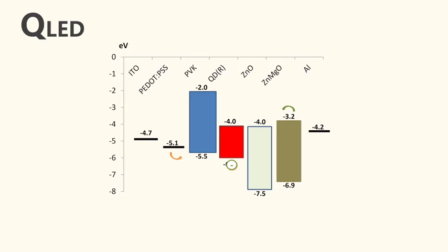This device adopts the EL characteristic of QDs. The full width at half maximum can be as sharp as 20 to 40 nanometers. The research for QLED is still at the lab stage. Commercial EL-QD products are not currently available on the market. Samsung and other QD LED TVs are now just utilizing the QD's PL property.